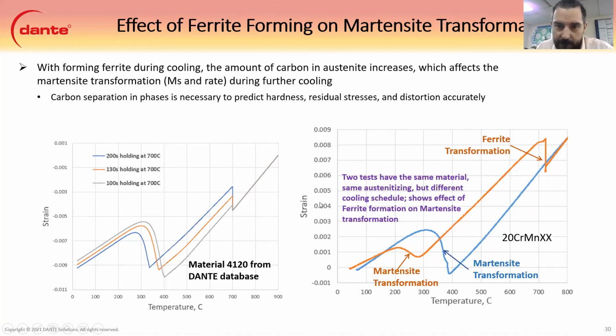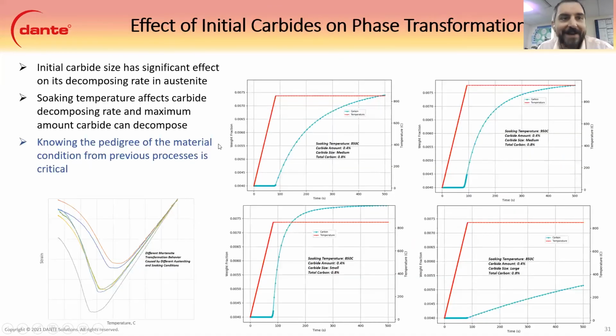And material, yep, covered that. All right, so carbide size. I was telling you earlier that we have a carbide dissolution model, and logically, larger carbides take a lot longer to dissolve than smaller carbides. The types of carbides matter too: if they're spheroids, they take a little longer than plates, like through ferrite and everything.